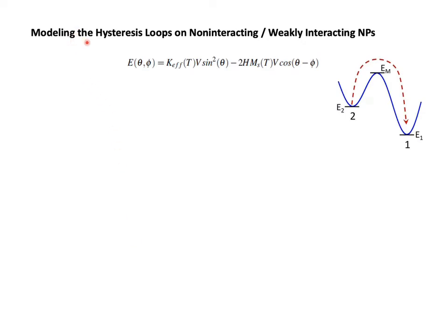Our modeling takes into account non-interacting or weakly interacting nanoparticles, and the energy as a function of the two angles theta and phi is a function of effective magnetic anisotropy, temperature, applied field and saturation magnetization.